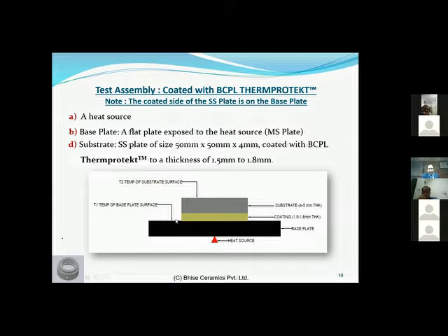Now, as you can see clearly over here, this is a coating of Thermprotekt that is applied on the substrate. The coating thickness is minimal, 1.5 to 1.8 mm. I'm stating this because when you coat it, there are bound to be some variations, and we have worked to make it very accurate.